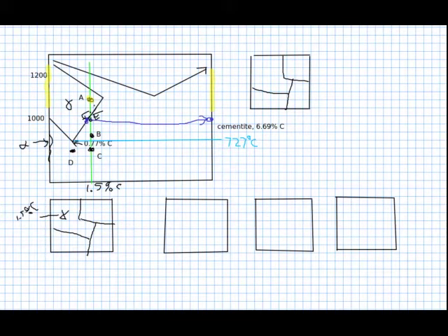And austenite was a solid. So as I transitioned from A to E, somehow the cementite formed. It's going to form at the grain boundaries because the diffusion rate is a little bit higher there. So the cementite is going to form, and I'm going to draw that on my diagram here.